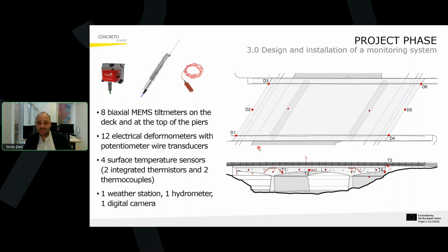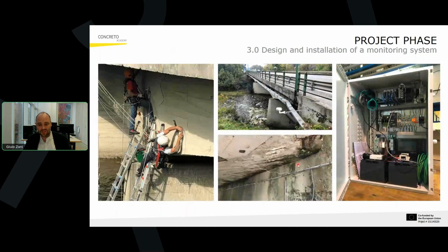We were lucky enough in this case to have a bridge which has a cantilever part. This means that we could fix the base of the transducer on the abutment, and then the head of the transducer to the intrados of the deck. This allowed us to measure the vertical displacement at the end of the deck, which is not always feasible on a bridge structure. The installation took place over a couple of working days, thanks to some climbers who installed the devices over the structure.